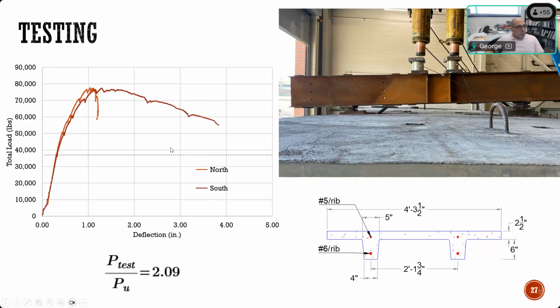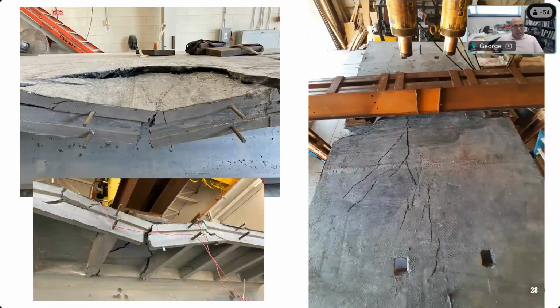We were able to load it with almost 76,000 pounds before we had a failure, and that gave a ratio of the ultimate load to the factored load from the truck of more than 2. So it can carry twice the capacity you design for, even for the factored load. And it shows here the failure, how it happens, pretty much like punching shear at the edge of the slab where we put the load.